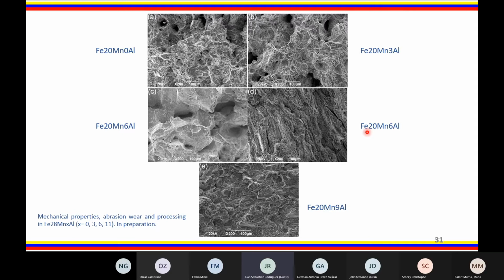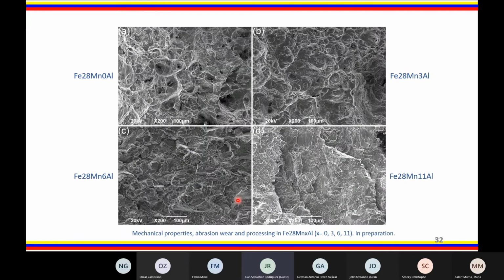By analyzing the fracture surface of these steels, we were able to observe the transition between a fracture surface of ductile materials, 0 and 3 aluminum, with the presence of dimples, up to the fracture surface of brittle materials, with the presence of cleavage. In the case of this manganese content, the transition between ductile and brittle is when the aluminum content is 6% by weight. For the alloy family of 28% by weight manganese, the same trend is observed. Up to 6% of aluminum has a ductile fracture surface, look at this. From 6% aluminum, the fracture surface changes and has the characteristics of a brittle fracture surface.